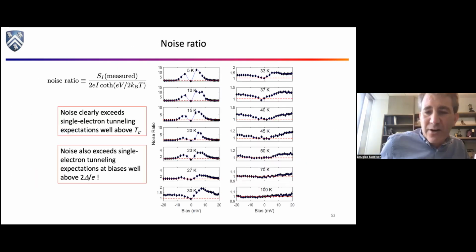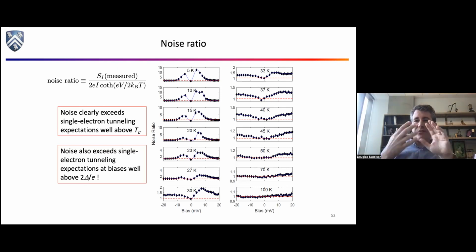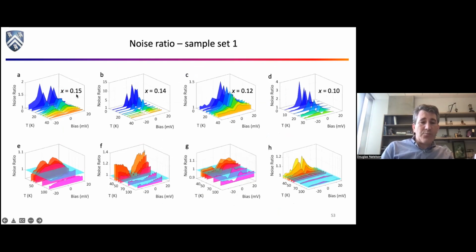So let me show you how carefully we looked at this. This is a pretty exotic result. We wanted to look at 4 different compositions of the superconductor. So here's X equals 0.15, 0.14, 0.12, 0.1. And the top row is that noise ratio as a function of voltage for everything below the superconducting temperature. But the bottom row is for everything above the superconducting temperature. And you can see there's a lot of stuff above this light blue surface for all of these, and it extends out to pretty high voltages.